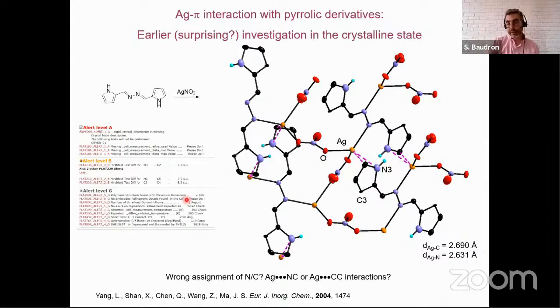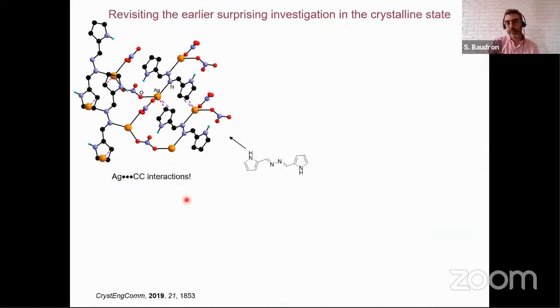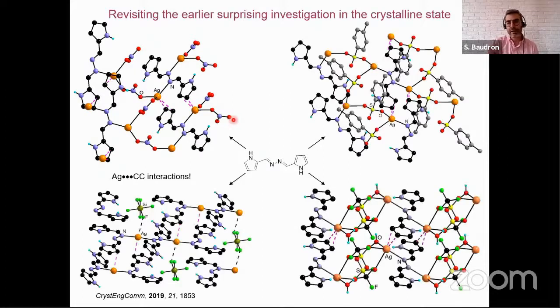So we went on to remake this ligand and study its assembly with silver(I) cation, redetermine the crystal structure, and indeed, what we observed was a carbon-carbon bond interaction with the silver(I) cation. We also studied it with a whole variety of silver salts, and in all instances, this was the same mode of assembly, which is consistent with the results we have observed with our dipyrrin ligands.